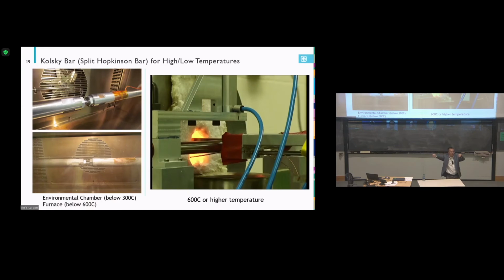Then the second bar uses another actuator and just moves forward to make everything contact. Then immediately we fire the gun and the specimen gets compressed. The whole process we control to be less than 1 millisecond. Everything is computer controlled. And to simulate the quenching process, we leave like 15 seconds, 30 seconds, it's up to you. Then we have to separate the bar.